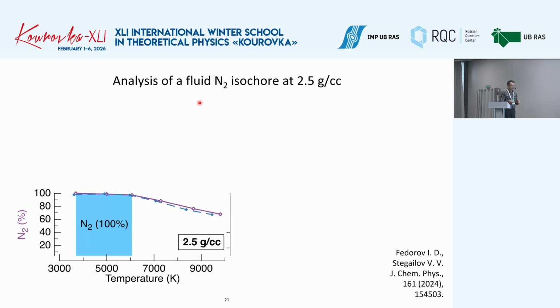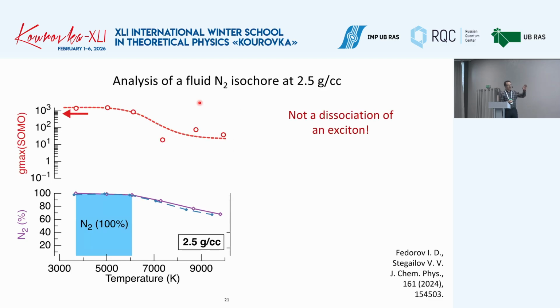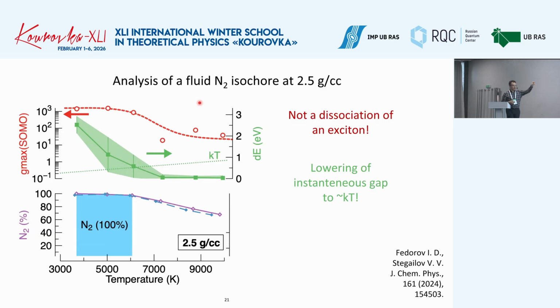And if we consider some isochore, for example, 2.5 gram per cubic centimeter, we see that molecular fluid exists up to very high temperature. Excitons can form, but they do not dissociate in nitrogen. But the gap becomes very small, and at this point, spontaneous formation of excitons begins.